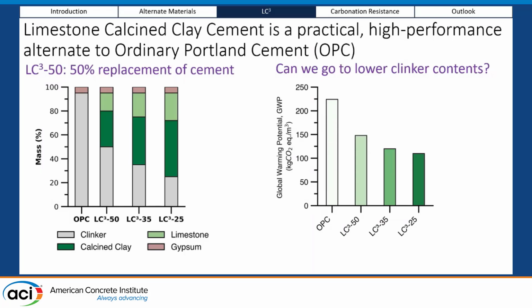So comparing OPC and LC3-50, we have about 50% replacement of cement with calcined clay and limestone. The question is, can we go towards lower clinker contents? By that we mean, can we go towards LC3-35 and LC3-25, with about 35 and 25% clinker? In this curve, you see the global warming potential, and we have 4 different kinds of mixes, OPC through LC3-25. We definitely see a decrease in the global warming potential compared to OPC, but the biggest jump is from OPC to LC3-50. There is a dilution factor here that should be taken into account.